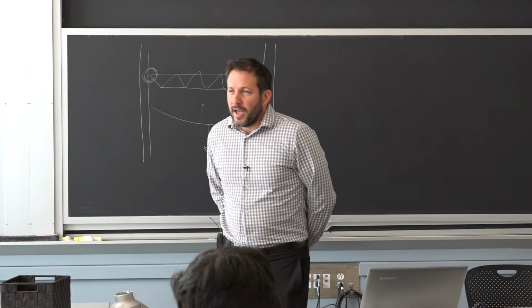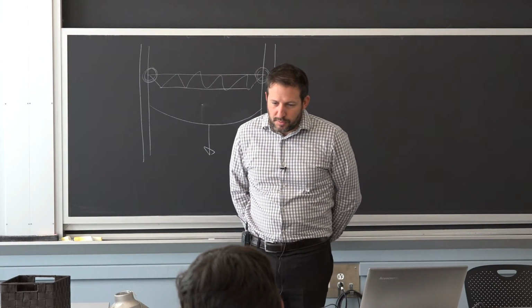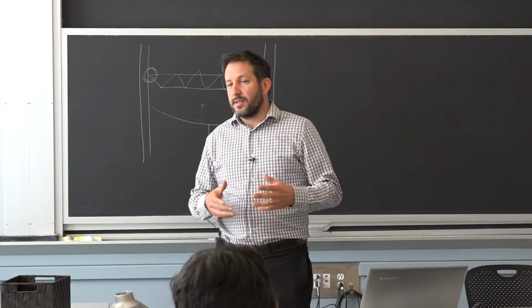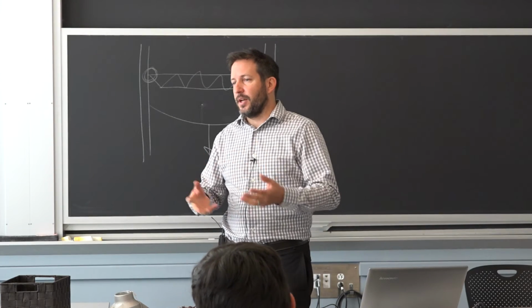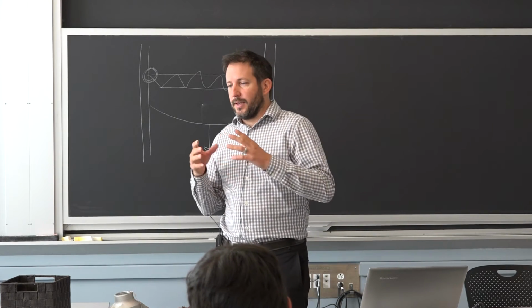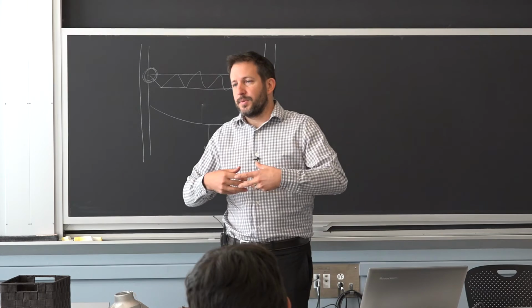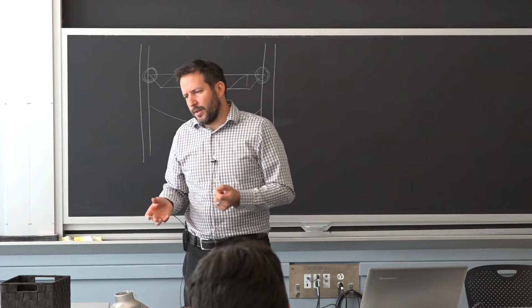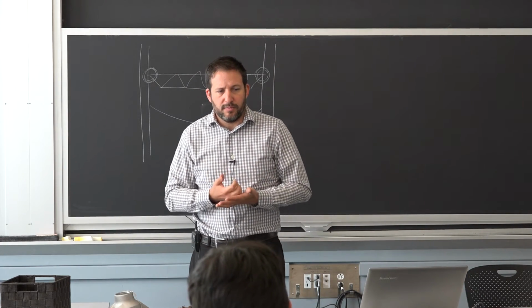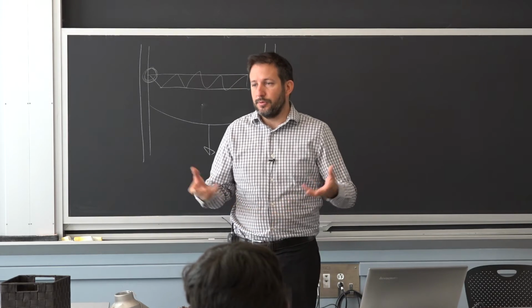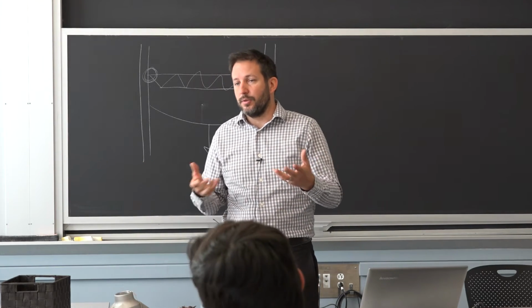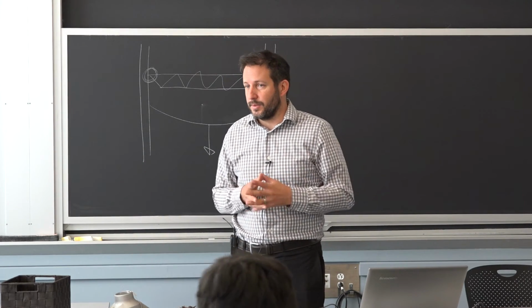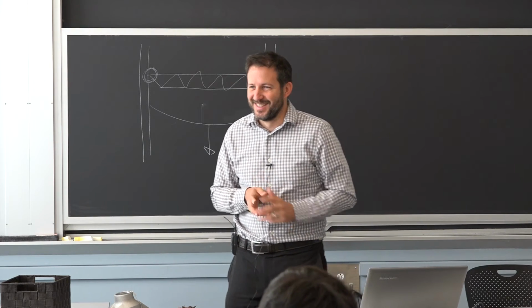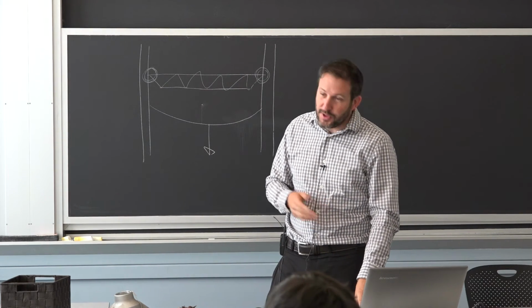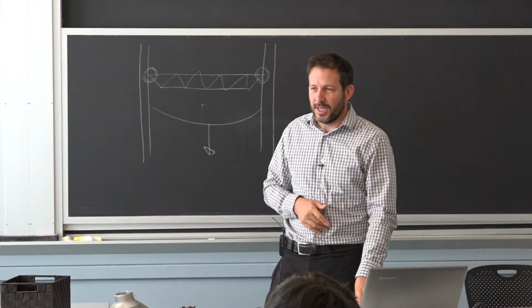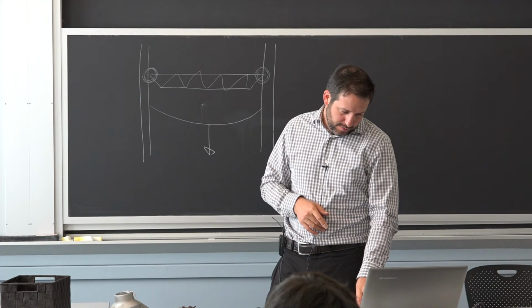Before you do it in a vacuum, a lot of times you will have a shielding gas atmosphere. So you put it in nitrogen or argon, and that is less expensive. It's just putting on the pressure. And I'll add one thing with respect to vacuum: sometimes you will lose some of the low weight alloying element that goes into the vacuum. So there are some pitfalls, but you don't get oxidation. So you have something that helps you.